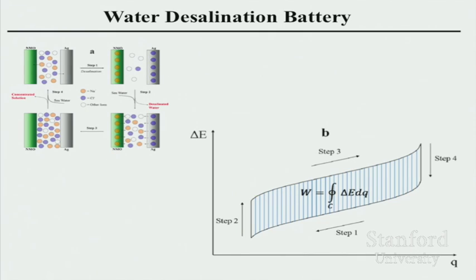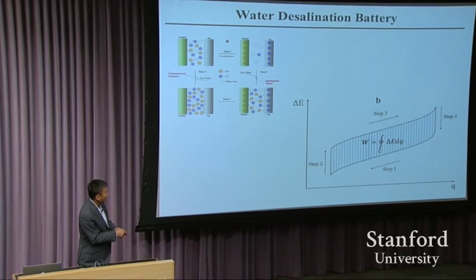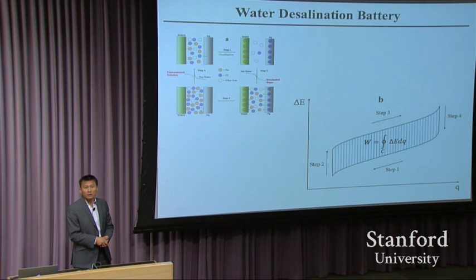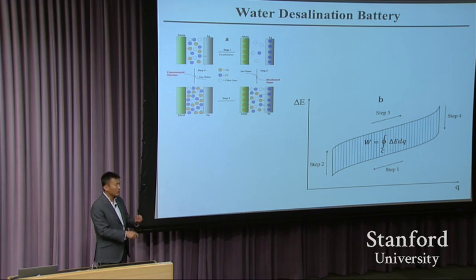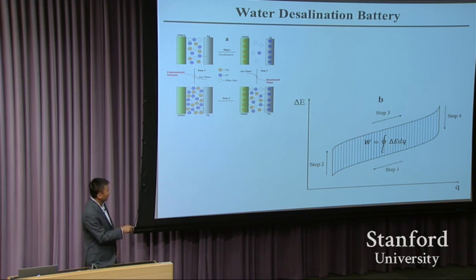So this is a curve you will expect. What happens, you start right here. This is the beginning. Step 1, you discharge the battery, put sodium into the crystal structure and chlorine into the crystal structure of the electrode, and then you flow out the fresh water and flow in the seawater. The voltage will jump up, and then you do the charging and come back. This is the voltage versus the charge curve. This is also the voltage versus the amount of sodium ions or chlorine ions you put in or take out. So this whole loop